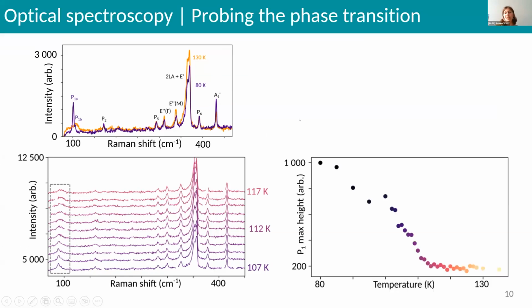If you plot the height of P1, you have two different behaviors: one before the phase transition, where it is almost constant, and one after, where it increases rapidly. So you can determine an approximate phase transition temperature of around 112 Kelvin.